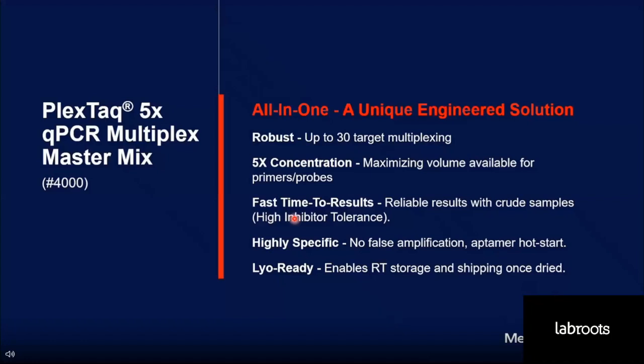This is our all-in-one solution. It contains engineered polymerase. This polymerase is hot started using aptamer technology. And the entire mix is 5 times concentrated, which means you have a lot of free volume for primers and probes, but also for samples. And this is of particular relevance as PlexTaq is working very nicely with crude samples. So it's compatible with blood, with saliva, but also with food lysate matrices. On top of that, PlexTaq was developed in order to work in multiplex setups. So you can use it in real-time PCR multiplexing, but also in endpoint PCR multiplexing with up to 30 targets.